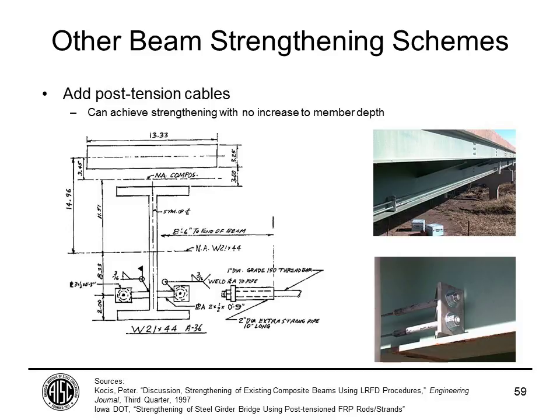So one last strengthening option is post-tensioning. Again, this is a good option for conditions where headroom may be a restraining condition, where you're not able to add to the depth of the beam because this particular scheme can be done within the depth of the existing member. So in this case, what you're doing is adding tension rods near the bottom flange of the beam, and those get tightened in order to create a compression force along the bottom that counteracts the positive moment that's in the beam. This paper here, discussion and strengthening of existing composite beams using LRFD procedure, is a good one to read if you're interested in learning how to evaluate and design this kind of strengthening.